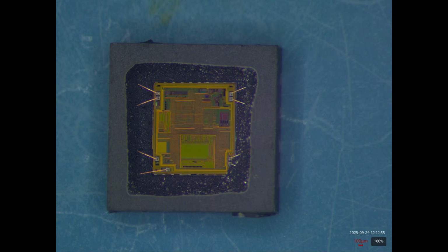So here's the sample after cleaning. We can see a nice square cavity around the die with all the bond wires exposed except the one in the bottom right corner, but we don't care about that area too much. The active circuitry is all fully exposed, and no damage outside the intended etch cavity.